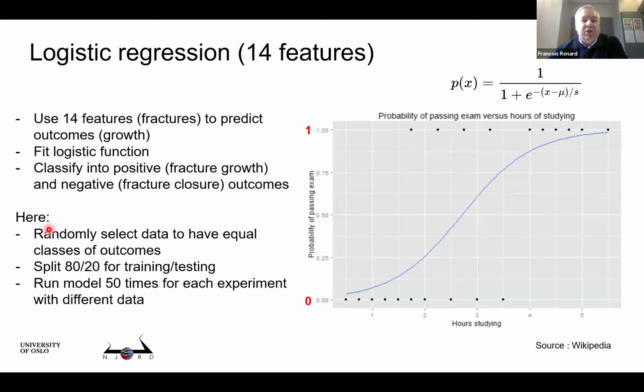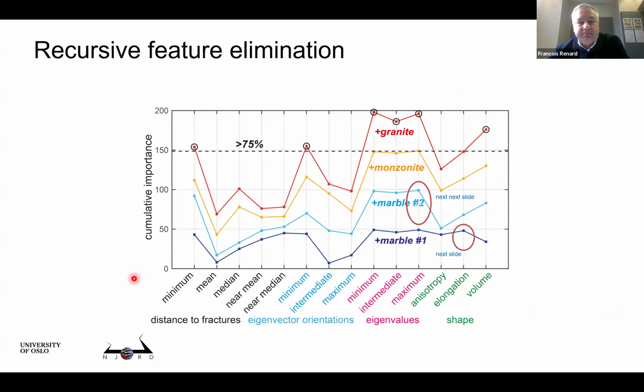And then we use the machine learning technique. We randomize the data to have the same number of fractures that grow and fractures that do not grow. We split between 80% training and 20% testing. We run 50 models with different data. And then we analyze the data by feature importance. So we have the 14 features, and we just cumulate between the samples.